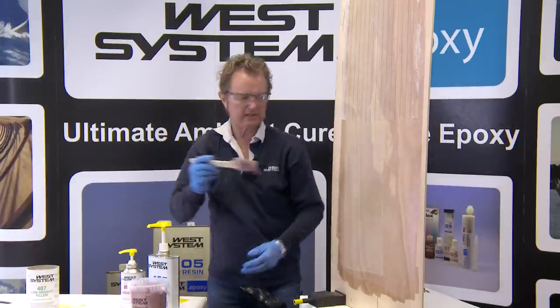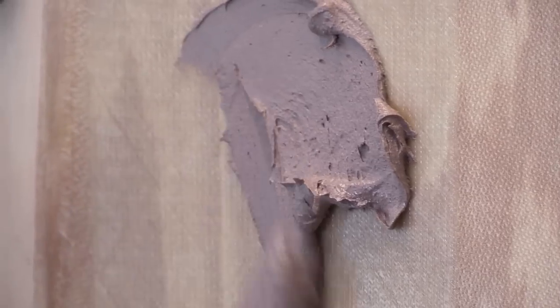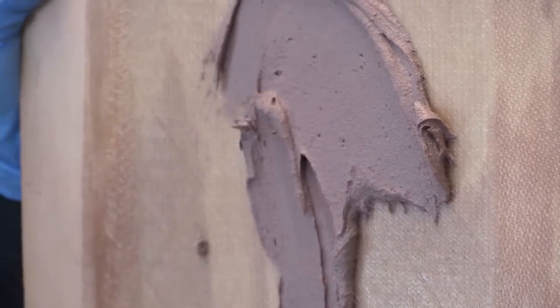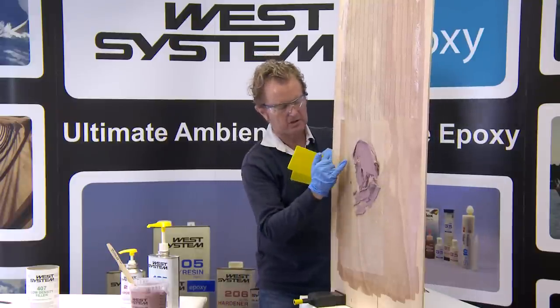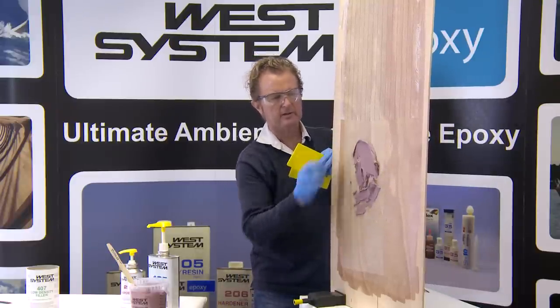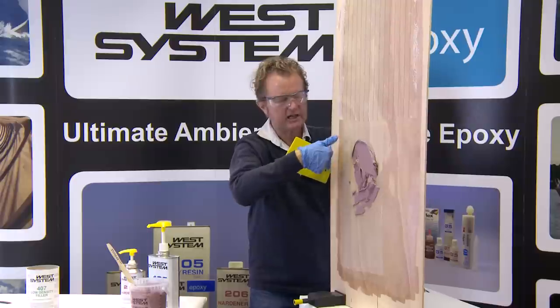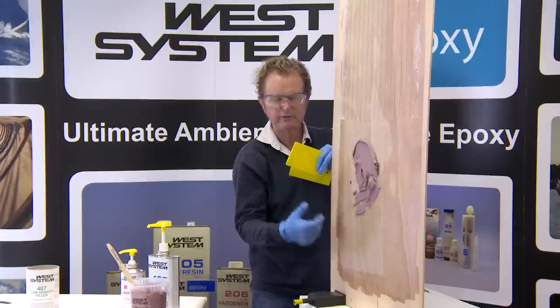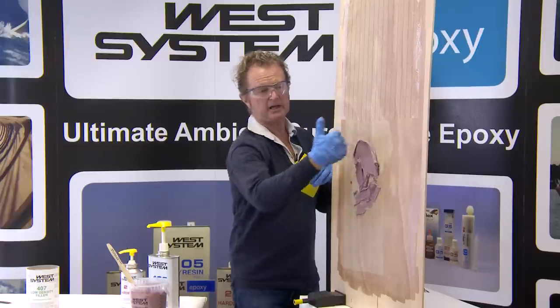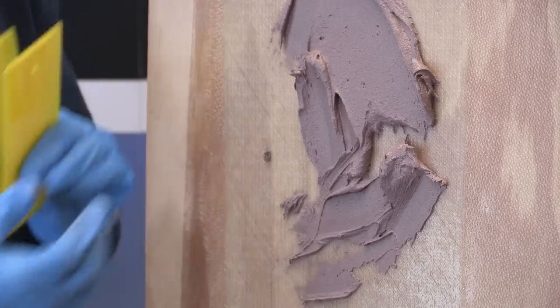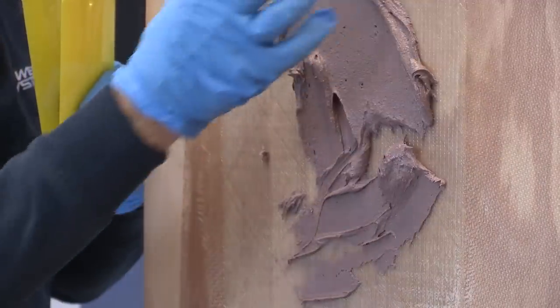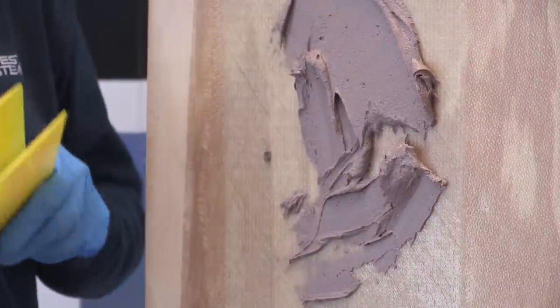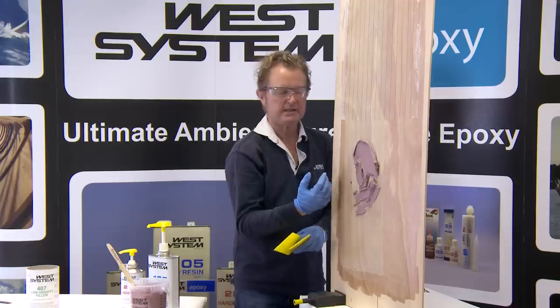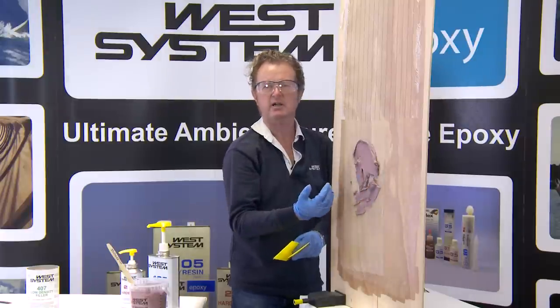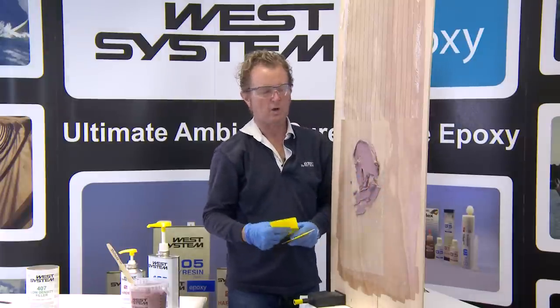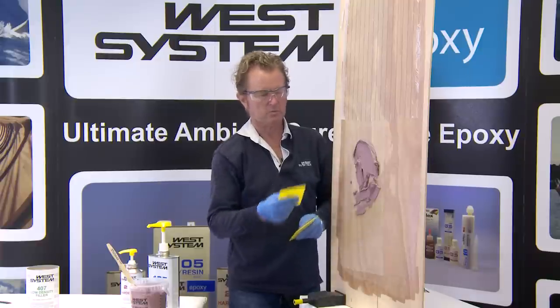I can use my mixing stick now to apply that to the work. One thing to mention is that the surface of my sheath part here is as sticky as masking tape. That's the perfect point at which to apply this filled coating. If it's really, really wet, what will happen is you'll disturb the weave of the glass as you're trying to apply the filled mix. The whole idea is to smooth this surface out and remove the texture of the woven and the biaxial fabric with the filler.